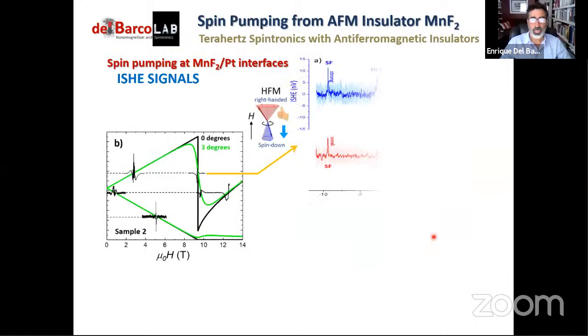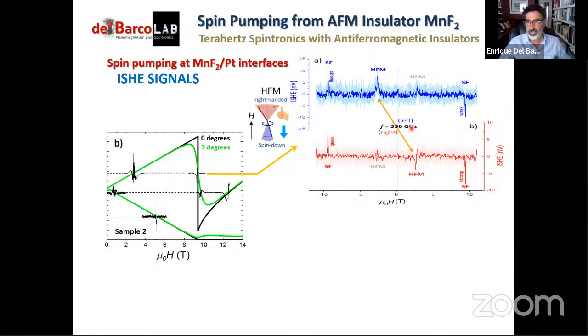But nicely now, what we can do, for example, if we go to 336 gigahertz, so we're just cutting the energy landscape along this line, we can see at positive fields we expect to have one peak and another peak, right? And this is what we see, one peak and another peak. But now we reverse the magnetic field, and then we see a feature here and another feature there. So this is actually time reversal, so we expect to see equivalent results, although not exactly the same in this particular case. But what I wanted to mention here is that we are able to work with both right-handed electromagnetic radiation and left-handed. And indeed, everything you see in red from now on is with right-handed circularly polarized microwaves. And in blue is left-handed circularly polarized microwaves.